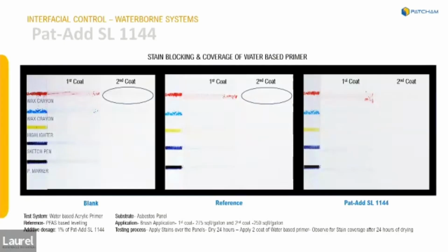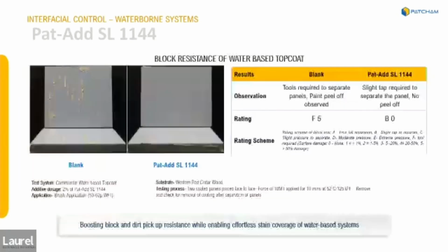This is the stain resistance of the first coat and the second coat of various stains. And then block resistance. Techniques are all described in the small print: heated, pushed together with pressure, and then taken apart. What we want to see is just full release, but the panel on the left you can see has stuck as we removed, and the layers have adhered to each other, and without on the right-hand side.